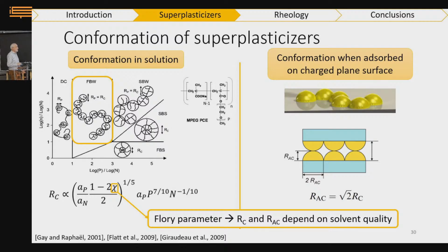Okay, so scale is really the right word, because the size of the core or of the blob, all of this is synonymous, actually scales with, as I said, the graft density and the graft length. But this is really a scaling law, okay? And you have prefactors that depend on the monomer sizes, but also on the solubility of the polymer. The property I mentioned before, that is how much the monomer prefers to interact with water or with another monomer. This is what we call the Flory parameter that describes the quality of the solvent. Okay, and it varies between 0 and 1 in the extreme.